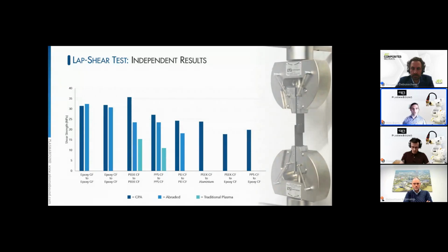Because traditionally, in order to see any benefit from the PEEK CF, they just didn't even need to treat or anodize the aluminium side. They just needed to keep testing it. It never achieved a substrate or an interfacial failure with the aluminium side.